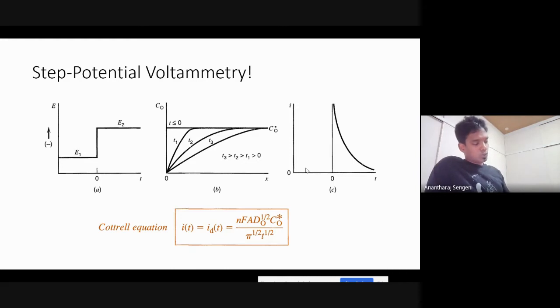And there is also a possibility when we use three-dimensional electrodes like foams, carbon cloths, and also titanium mesh. When we use these three-dimensional electrodes, even though we dip just the desired portion of the electrode into the solution, because of the capillary action of the 3D structure, the electrolyte reaches a larger area than what is actually dipped into the solution.